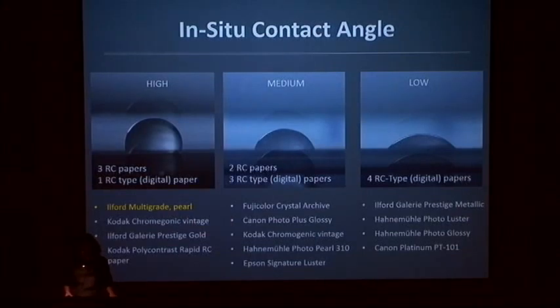These are our results. Previously, we inferred that RC prints were non-polar, but this is only true for some papers, not for all. Early RC prints were non-polar, but today this is much less likely to be the case. The image at the left concurs with the FTIR spectra. These are the most aliphatic or hydrophobic, and the ones on the right have the strongest carbonyl signal.